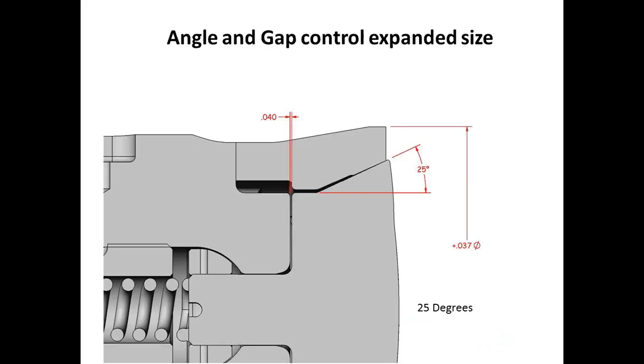These are just a couple examples. Often we use a 25-degree angle between the conical component of the mandrel and the ring, in which case we would have about a 40 thou gap between the back of the mandrel and the pad area, which would give us 37 thousandths of an inch on diameter expansion.